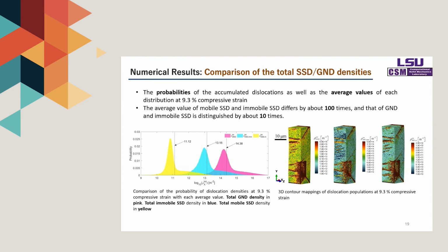The average values of each distribution at 9.3 strain are very close to the experimental observations in terms of the amount of accumulated dislocation populations. The mean value of immobile SSD is bigger than mobile SSD density by about 100 times, and total GND density is distinguished by about 10 times bigger than immobile SSD density.